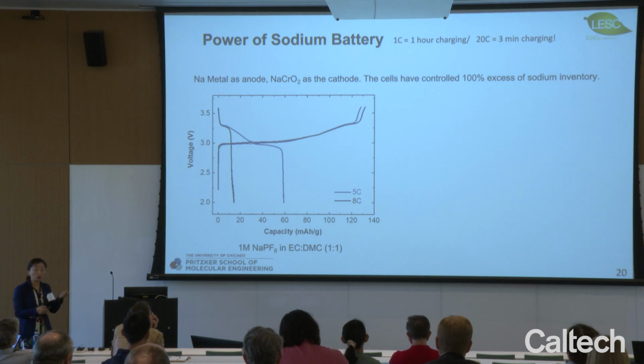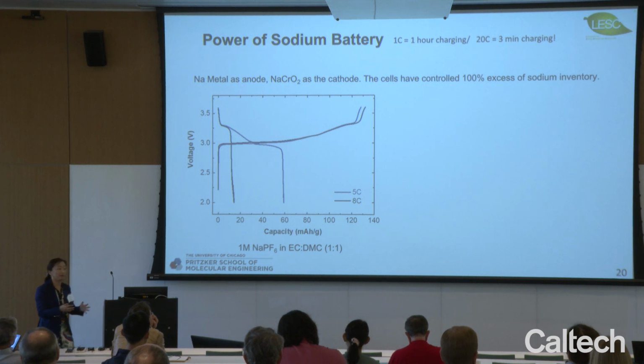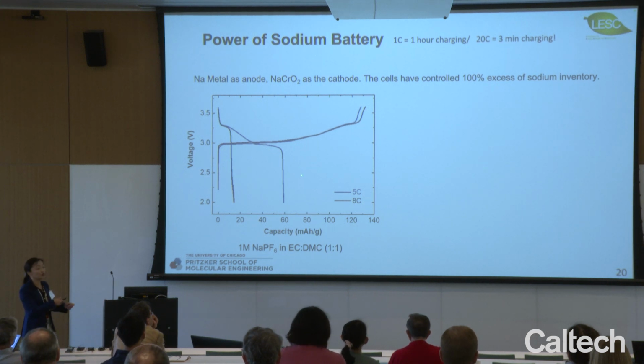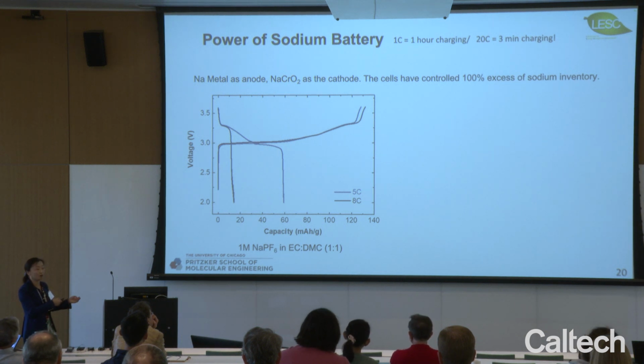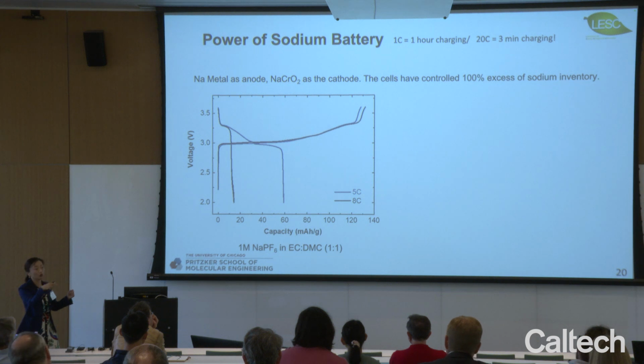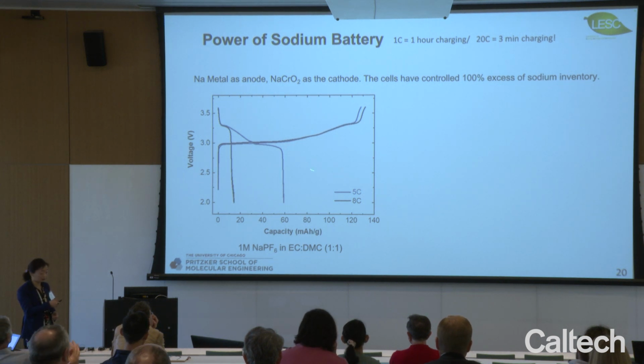So if I use sodium, an intercalation material, with a sodium metal anode, and I use the traditional electrolyte we developed for lithium, the cell, okay, this is not good, right? You charge, and then when you discharge, you get like 50% or 20% of the capacity. And again, I apologize for the jargon. When we say 5C, it means 60 minutes divided by 5, so it's a 12 minute charge-discharge. This is a pretty fast charge-discharge protocol we do for sodium.